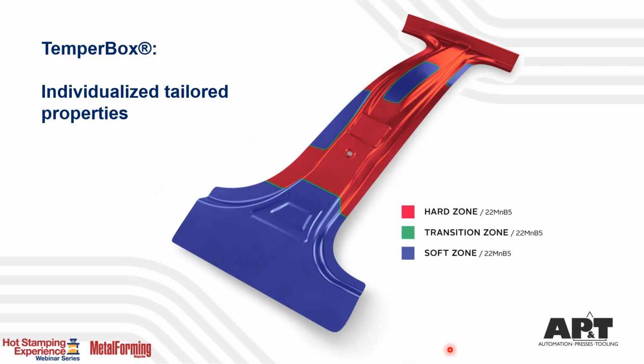So we can quite conventionally have the soft bottom of a B-pillar, for example, which is nowadays also done by many suppliers and many stampers out there. It can either be done in blank technology, tailored welded blanks to reach different properties in the bottom part for crash behavior. But quite interesting are those localized soft areas that I tried to pinpoint here in certain areas. And this is especially interesting nowadays also for electrified vehicles. In certain areas, when you look at the rollover tests, when you simulate rollover crash, we do need sometimes certain areas with higher ductility. If you would have a crash, those areas are not too brittle and would not break. So especially in these areas, localized soft zones are quite interesting.